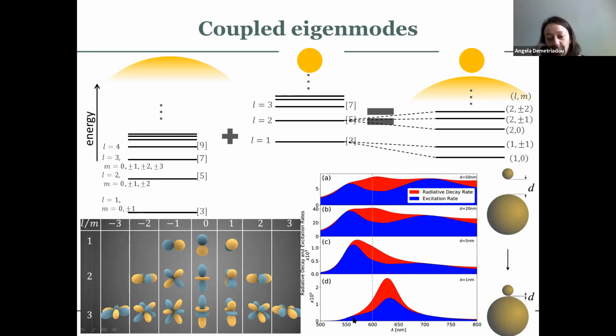So basically I do have other modes here. It's not only one mode as we thought initially, there are a lot of others. It's just these are the dominant ones. And the behavior between the radiative and the excitation rate remains the difference between them for the same reasons as you had them there for the very, very large nanoparticle. It's because there are modes that you're selectively not exciting with a plane wave.